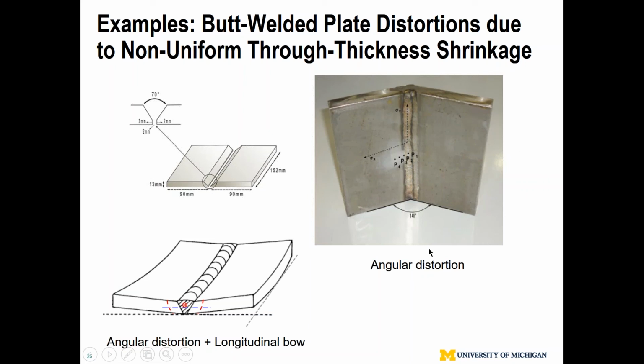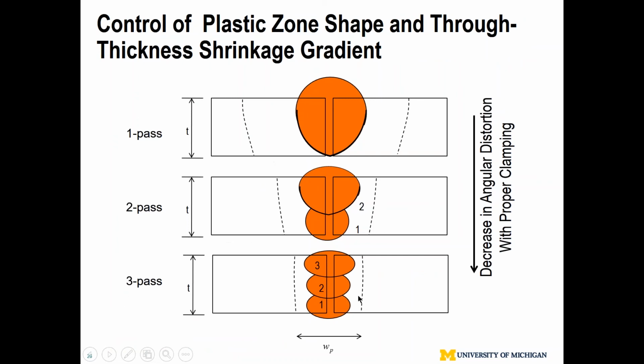So if I look at a single V joint, for illustration purposes, the red line here is the plastic zone shape, because it's not symmetric to the neutral axis of the plate. So you have angular distortion, and also the centroid of the shrinkage zone, the plastic zone, is above the neutral axis, so you get this longitudinal bow. This is the actual experiment done in France to support the international round-robin study. A few examples.